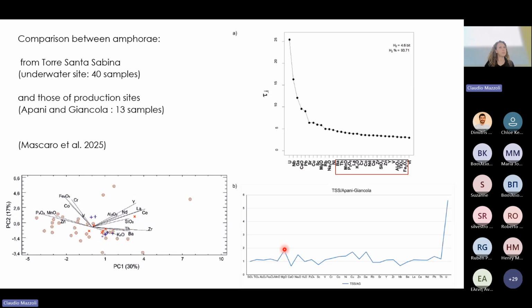While if you have positive values, it means that that element was enriched. While negative values determine that there was a leaching. Okay? Great. Obviously, somebody can tell me, okay, Lara, but I see that, for instance, there's enrichment in calcite. This means that calcium increases in quantity. And I can see that. But we have another problem: if I enrich something in an element, the average composition of all the others will change. Right? It's like you taking a cake and adding some chocolate, and then you measure the quantity of nutrients. It will change also the other ones.